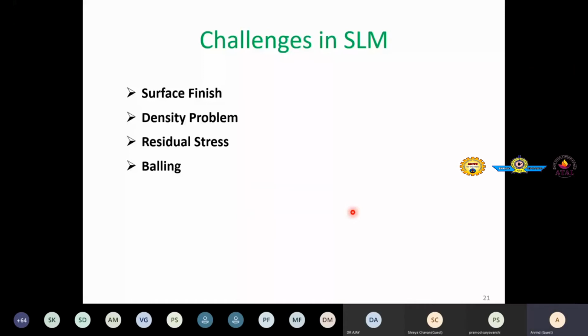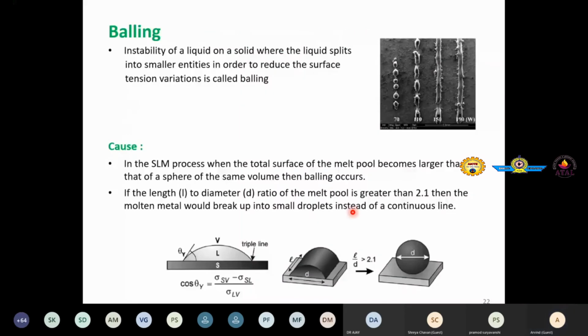Next problem is residual stress. I mentioned that since this process is layer wise deposition, a lot of thermal stresses are involved because of repeated thermal cycling, heating and cooling cycle, and it provides a lot of residual stresses in the part. One more challenge in the SLM is balling defect. We are going to see what that is in the next slide.